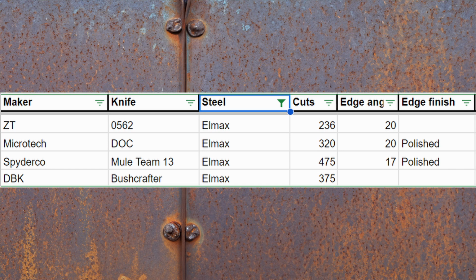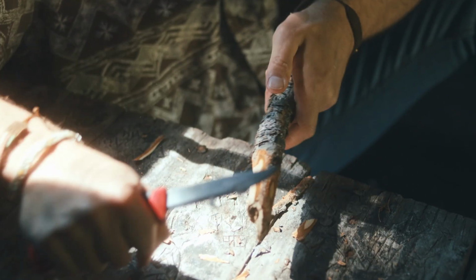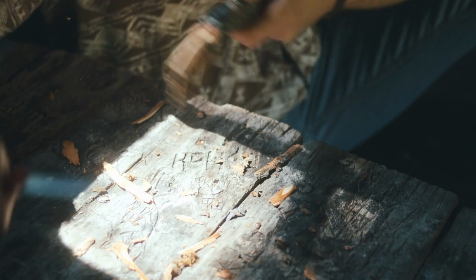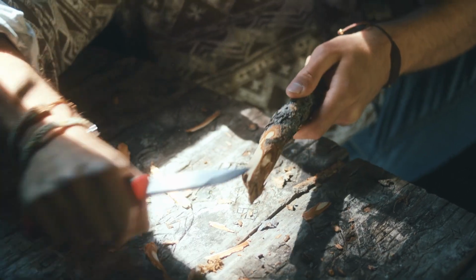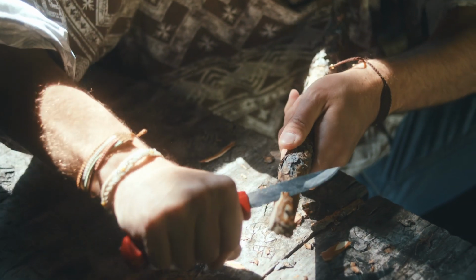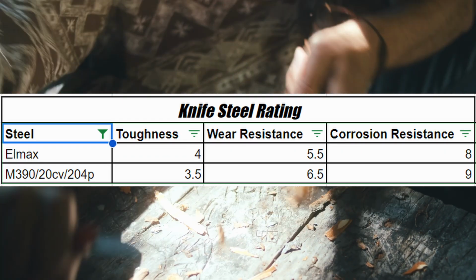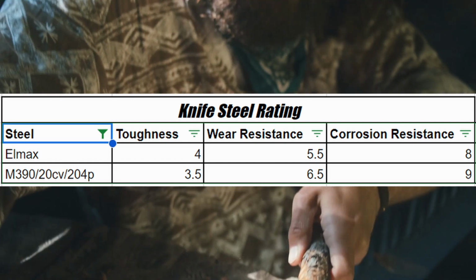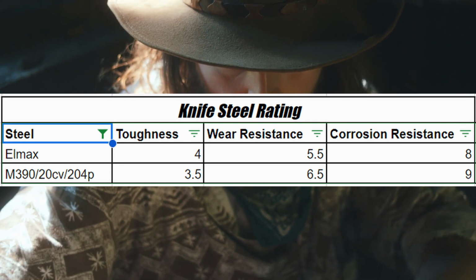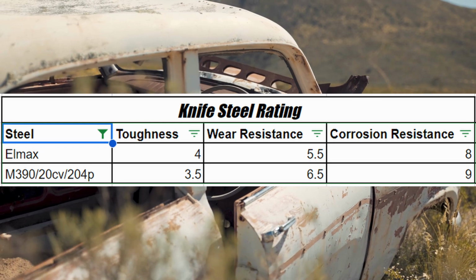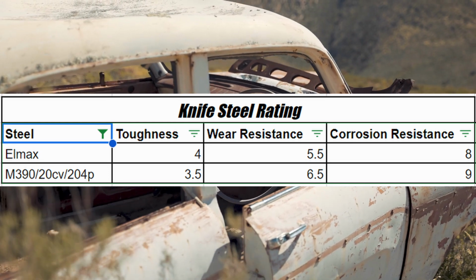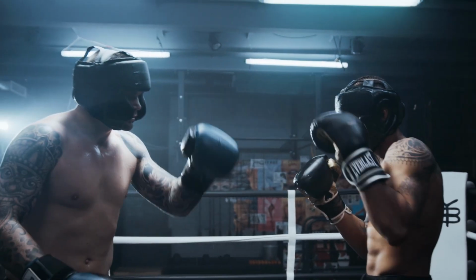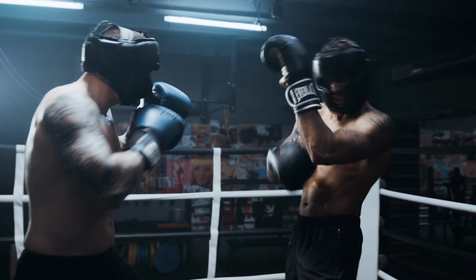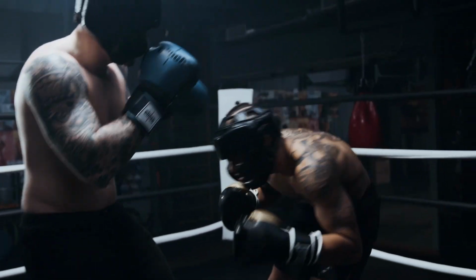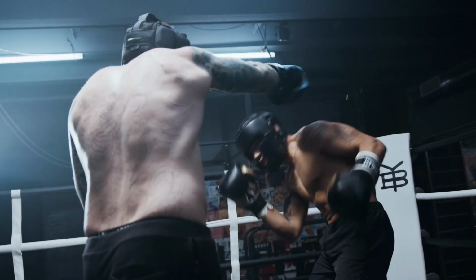But how does it compare against other stainless super steels in these real-world cut tests? Now that we've established that better toughness allows for more edge stability at lower edge angles, which in turn leads to better edge retention, let's compare against what is probably Elmax's biggest rival, M390. M390 is often touted as marginally better than Elmax because M390 is slightly more rust resistant and has slightly more wear resistance. The only way to see the difference definitively would be to compare the same model of knife at the same edge angle. This is because of the difference in Rockwell hardness targets seen between different manufacturers, and sometimes even the same manufacturer just using different steels.